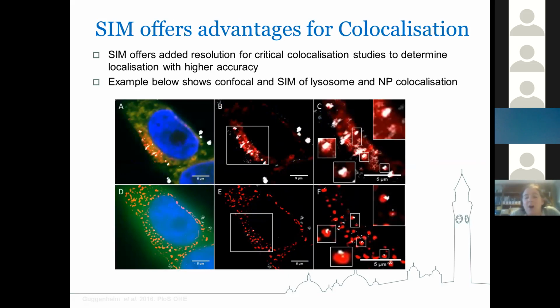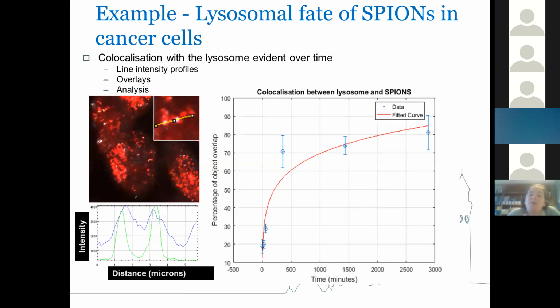Again, we can resolve some of these larger clusters and see whether they are one large lysosome, for example, or several just closely located lysosomes. Which again is important because one of the measures of toxicity could be lysosome size and lysosome acidity and things like that. So we can also then, using the reflectance signal of the particles, look to see what happens to the particles, so whether they degrade inside the lysosomes.